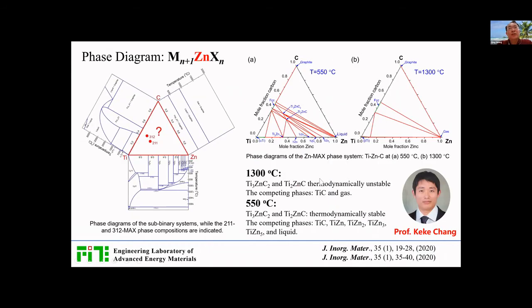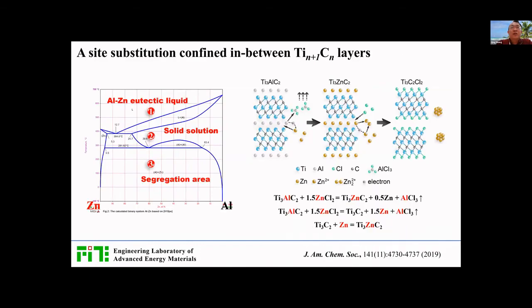But how to make these new MAX phases? So we made some simulations on the phase diagram. Here we see that the zinc MAX phase only exists at very low temperature, around 550 centigrade. But for experimental synthesis, at low temperature the kinetic process is very slow. So that's the reason we cannot easily get these new MAX phases. Here we found a new synthesis approach to make these new MAX phases.